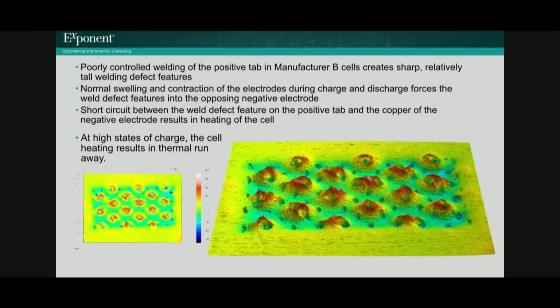Considering the available data, we can propose a failure scenario. Poorly controlled welding creates relatively tall welding defect features. Normal swelling and contraction of the electrodes during charge and discharge forces the weld defect features into the opposing negative electrode. Short circuit between the weld defect feature on the positive tab and the copper of the negative electrode results in heating of the cell. At high states of charge, the cell heating results in thermal runaway.